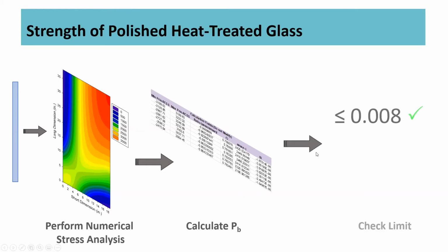And then what we're looking for is either we're greater than or less than 8 in 1,000. So E1300 specifies this kind of cutoff point that is said if our probability of breakage that we calculated is less than 8 in 1,000, then our design works. If it's greater than 8 in 1,000, then we have a problem. So this is going to be our check that we need to show that post-polishing, we still have a probability of breakage that does not exceed 8 in 1,000. And I'm happy to discuss any of this process later on in more detail, but we're going to leave it there for today.